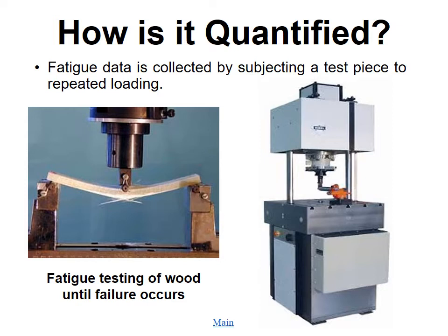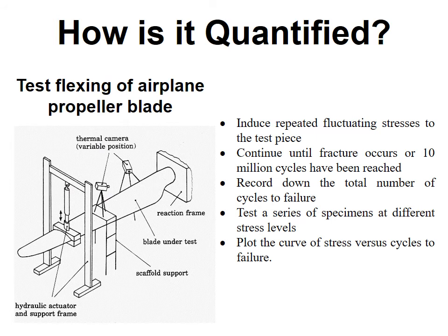The fatigue properties and data of a material can be obtained by subjecting it to repeated loading using a Wöhler machine as shown in the slide here. From components that are small to items that are big, the fatigue properties of different metals can be obtained using the Wöhler machine. In this diagram, an airplane propeller blade is being appraised. A series of specimens are subjected to reversals of stresses, each at a different value, until failure occurs, or until 10 million cycles have been endured. The total number of cycles to failure is then recorded, and a stress cycle curve is plotted from which we can establish the relationship between the stress and the number of cycles to failure for any particular type of loading.